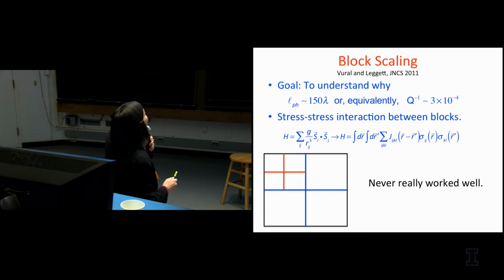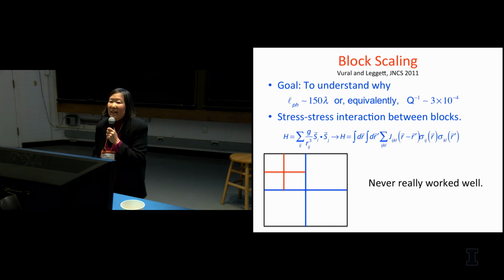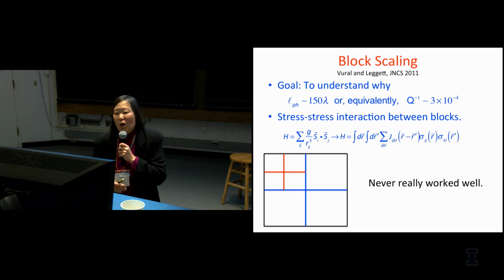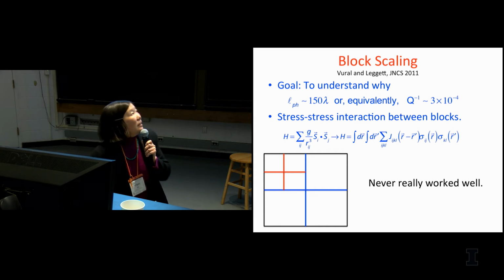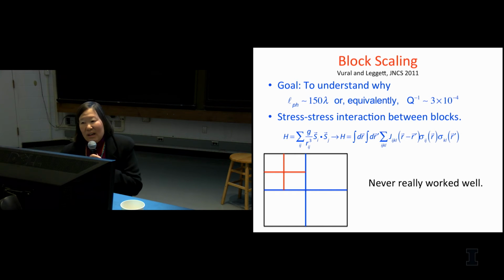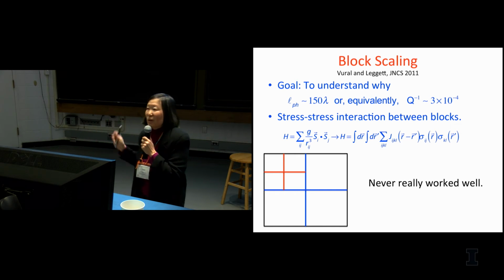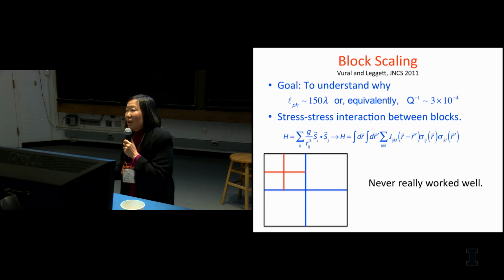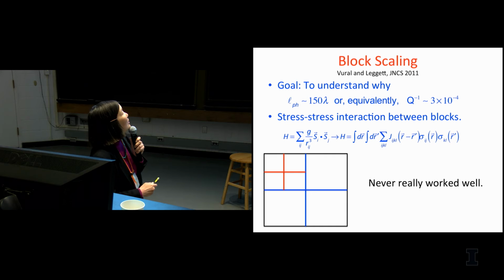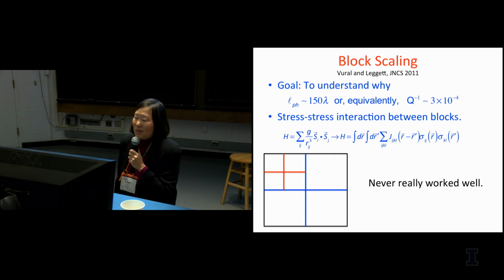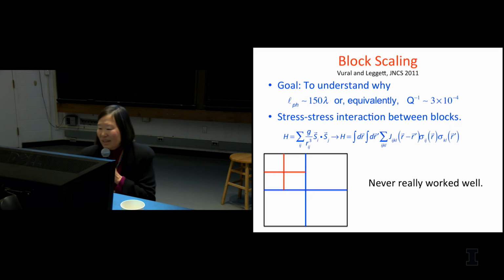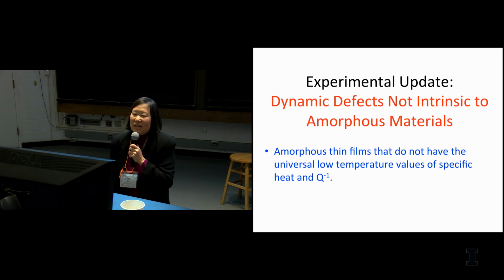Tony always had the idea that we could do some sort of block scaling to get these universal values. The idea would be that you have these little blocks that you could describe by some stress tensors, and then you put in the dipolar coupling between the blocks, you scale to a bigger block, and the hope was that you would scale and flow to these universal values. Unfortunately, Dervish Vural, who's here, and Tony worked this out, but it never really worked. It didn't really give them an ironclad argument for these universal values. You'd really like something like some topological constant. So it remains a challenge to this day.